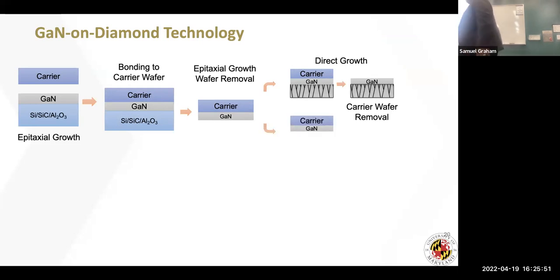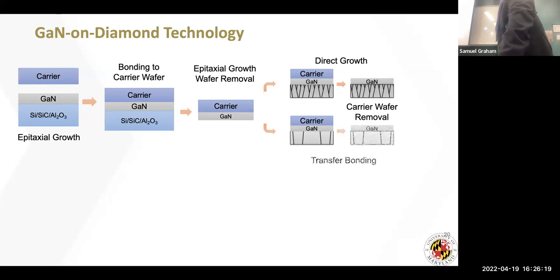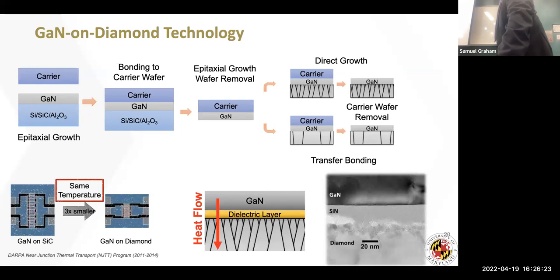The other way is, of course, we're going to try the bonding. So what happens if I try to take the gallium nitride and I'm just going to take now high quality diamond? One of the things I want you to notice is that these lines on here are different than these, and it's on purpose because I have to nucleate the diamond, so I get really small grains near this interface. Now I can take single crystal diamond, I can take large grain polycrystalline and bond it directly. So the small crystalline diamond has a large thermal resistance, so I can get rid of that. So these are nice things about going through this process. And so then I can just go through the wafer removal, and this is called transfer bond.